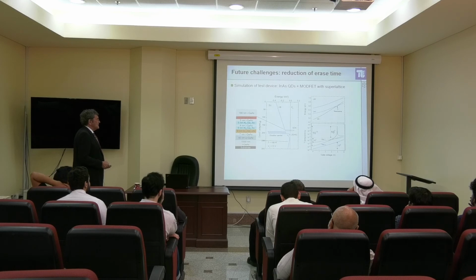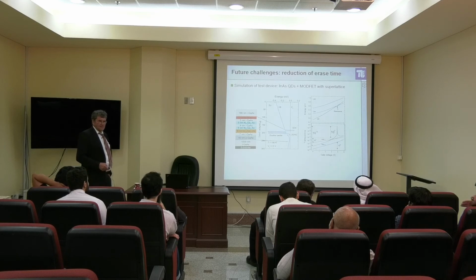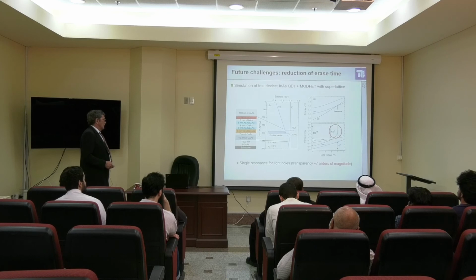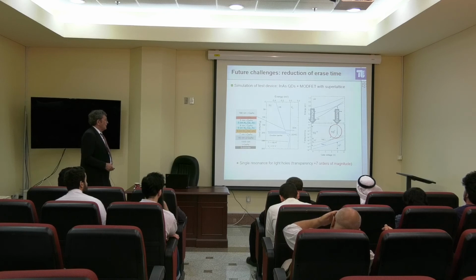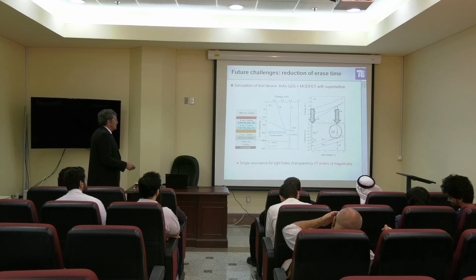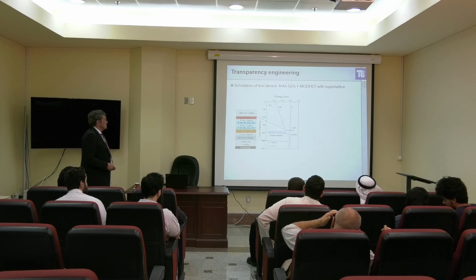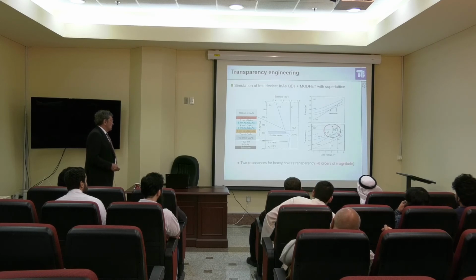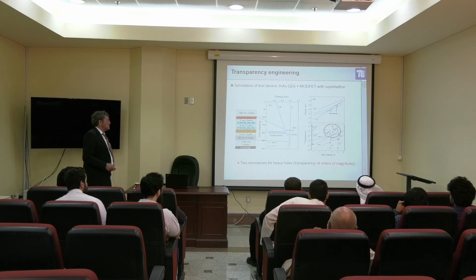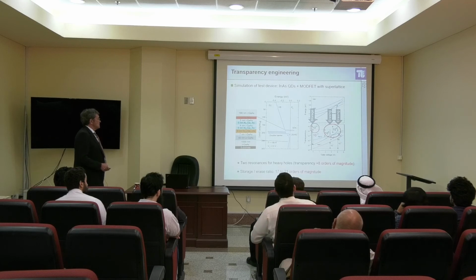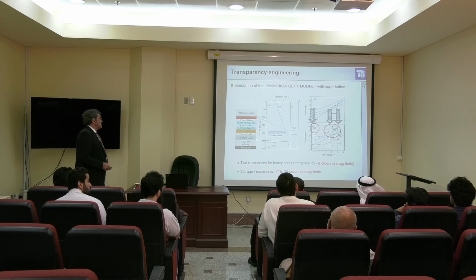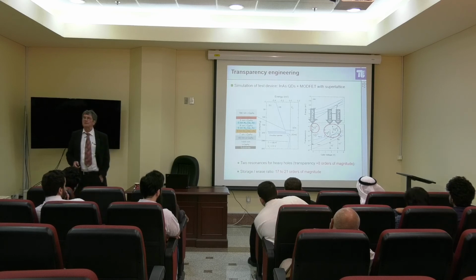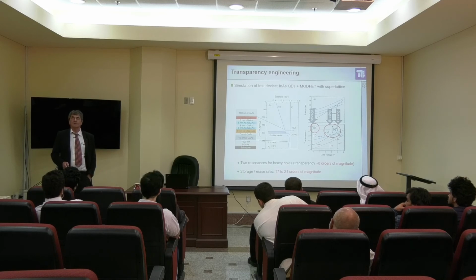But it works now, and you can see that you can modify the transparency by at least 7 orders of magnitude by changing just a few tenths of a volt. Isn't that fantastic? And that is working. Single resonance for light holes, 7 orders of magnitude. You have a storage position and an erasing position, here at 0 volt and here at 4 volt, which is very easy. You can get actually more. You also have a resonance for heavy holes, 8 orders of magnitude difference. You have different erase positions. So the storage-to-erase ratio is between 17 and 21 orders of magnitude.